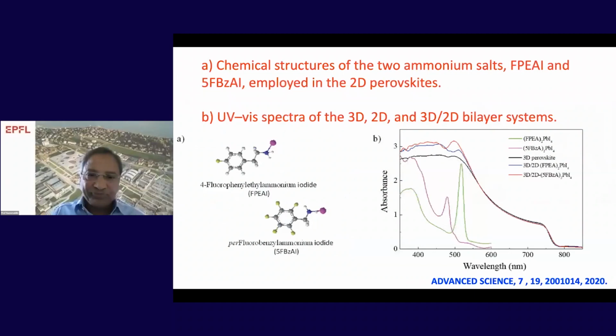perovskite solar cells. So here I have taken two examples: the fluorophenylethylamine cation, and the second cation example is pentafluorobenzylamine. You must have recognized we are using fluoride groups in order to create hydrophobicity, because the hydrophilicity of the perovskite is the biggest problem. So by having this type of hydrophobic cation, it can prevent humidity-induced degradation. That's one of the main reasons for having the fluorine substitutions.